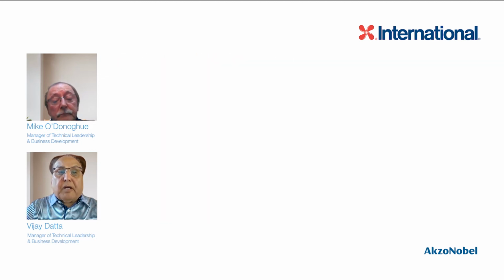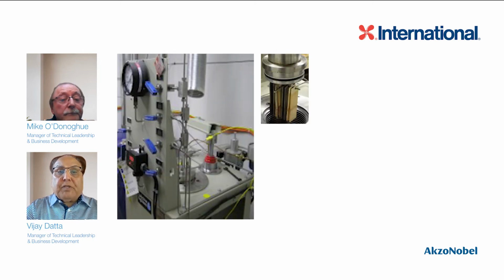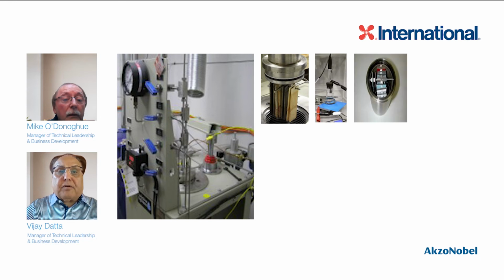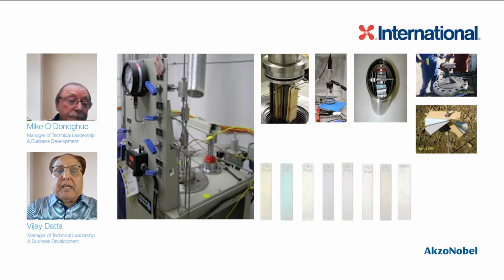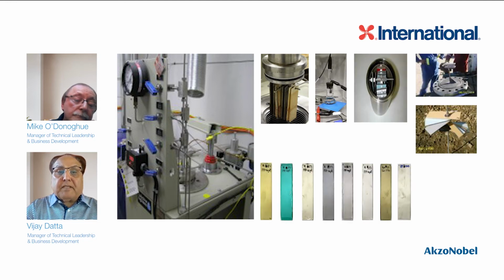Mike, you were talking about the autoclave test. Here are some top pictures showing the various autoclaves. What we do is we run these, it's like a pressure cooker. So we'll prepare the panels and put them into this autoclave test and expose them at various pressures and temperatures and the environment. So testing is really, really important. Lab testing also is really important to have a field testing.